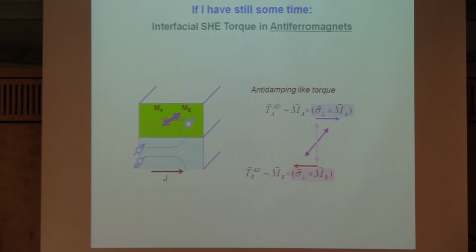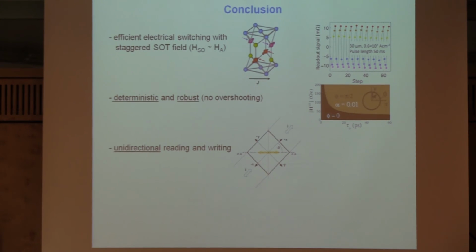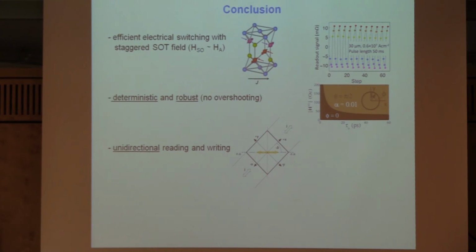There is a question. Can you show something on the equilibrium discrimination between the 180 degree domains? How do you measure and identify the resistance? Because AMR, which is also linear dichroism, would in principle be independent if you switch by 180 degrees, so you would have the same signal after a 180 degree rotation.